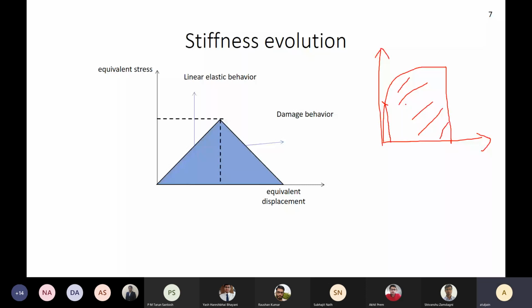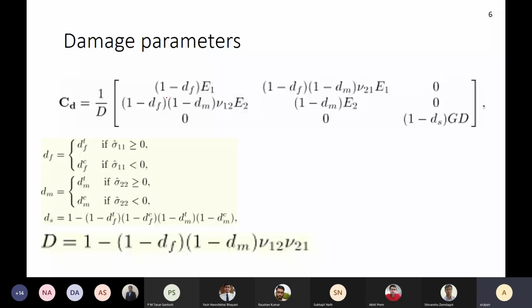This we have to derive experimentally and input into Abaqus. Abaqus is going to model it like this. It says that the response of the material is bilinear. It increases, and then the equivalent stress versus displacement, if I plot it, will decrease. Region 1 is linear elastic, and after damage begins, the stiffness starts reducing. Based on the slope of this line, you can calculate the initial Young's modulus and the Young's modulus after that, and based on this you can calculate the different damage parameters depending on which damage has taken place, by looking at this curve for the fracture energy.